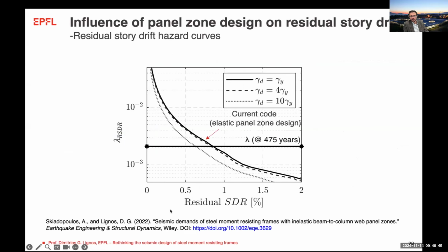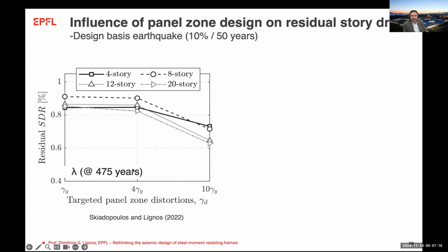And by doing so, what you can see is that if you are looking at design events with a return period of 475 years, the reduction you get on average on the rate of exceeding residual story drift ratios is about 30% when your design is allowing more panel zone shear distortion relative to what is code compliant right now. And also, if you're looking at different heights, you see that the residual drifts would actually reduce quite a bit. If you are looking again at return periods of 475 years, that in the US at least, this would be a design level earthquake.